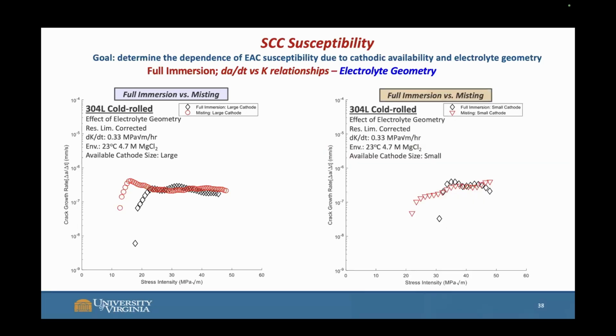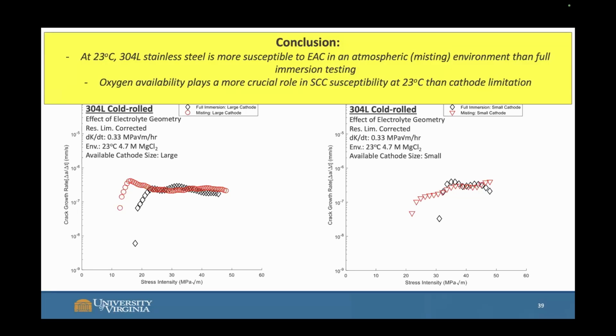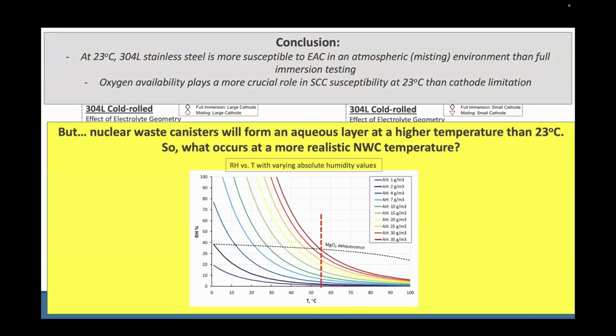So we also did it with the small cathode samples where we physically painted them. We did a full immersion small cathode and an atmospheric small cathode, and we still saw that misting was more susceptible than full immersion. So this would indicate that oxygen availability is going to be playing a more crucial role for SCC susceptibility at room temperature, or 23C, than cathode size limitation. But it's going to be a while until the canister hits 23C. It's going to hit 55C first.